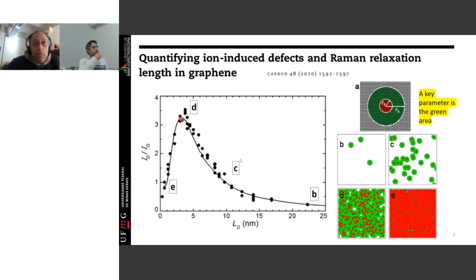And what we realized is that this maximum is, you already saw that there is a green area here. I didn't talk about this green area. I explained the red, that is the damaged. And the green area is an interesting aspect where if an electron generating the Raman scattering happens to be in this range, in this area here, it knows there is a defect there. If you are far away, you don't know. So there is a correlation area here, which is inside this range, this area that's green. The process knows there is a defect there. The electronic structure is connected to that defect. If you are far away, it's not. So what happens is that you reach a maximum when there is a coalescence of this green region. And above this situation, what you do is you destroy the material. So this is why it decays, okay?